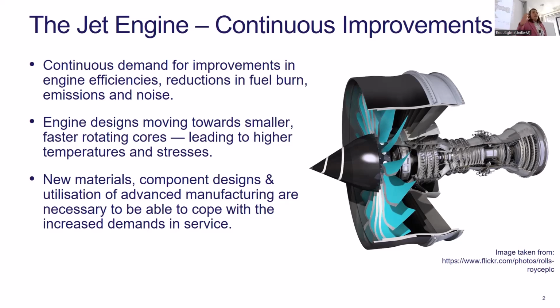And as a way to achieve this, there's loads of different motivations, including the geared turbofans and the like that some companies are looking into. But a more readily achievable way is to reduce the core of the engine and create a smaller, faster rotating core, right? So we increase the temperatures in the engine itself within the core, but we also increase the stresses that the core is experiencing. As a result, we need to look at the materials that we're using because those materials need to withstand both higher temperatures and higher stresses. And we also can look at the component designs because advanced manufacturing offers us that capability to change our component geometries, introduce more complex cooling channels and the like, so that we can cope with the increased demands in service.